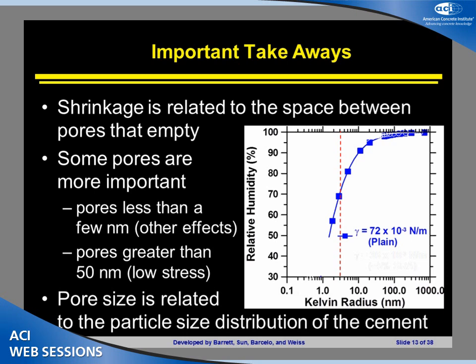All right, so shrinkage is really related to the size of the pores that are emptying, all right? Pores smaller than a few nanometers, we worry about other things. Pores bigger than about 50 nanometers, they're really not small enough that we start to generate significant stresses. So we're going to focus in on this region right in here. From about 3 nanometers up to somewhere around 20 nanometers is really the range that we're interested in for most of the shrinkage that we're going to be talking about.